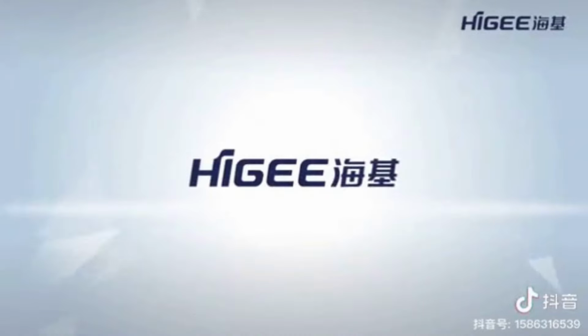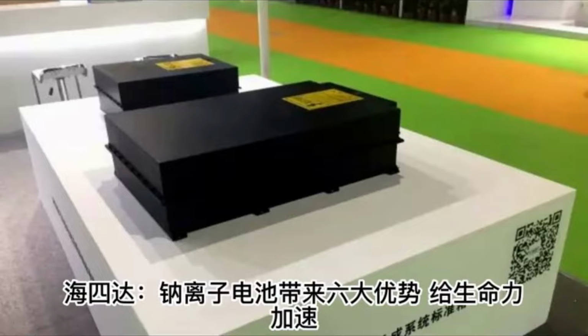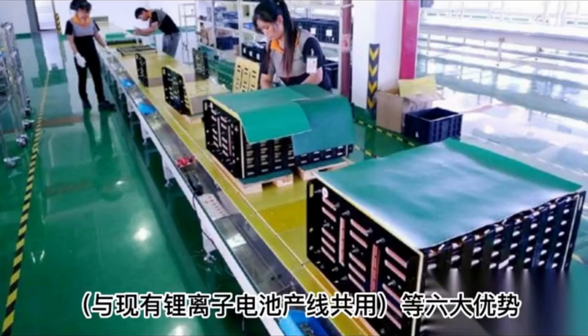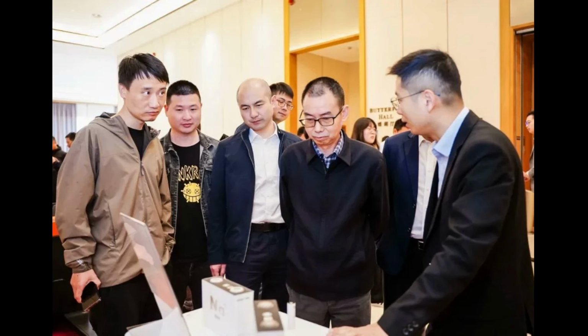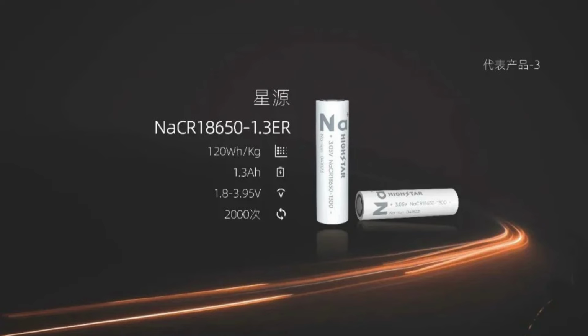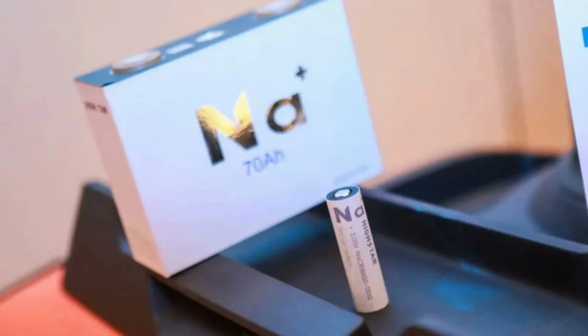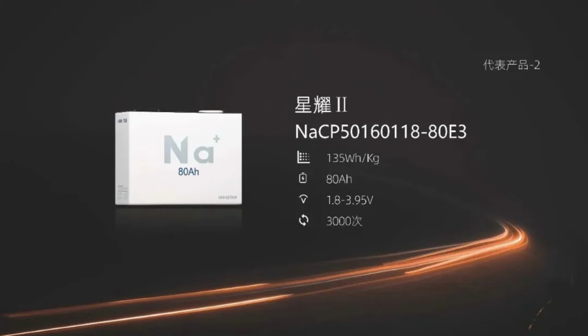The next on our list is Jiangsu HIGHSTAR battery manufacturing in China. The company recently published 3 of its Star series sodium-ion battery cells, which are cylindrical and prismatic cell formats, having a capacity of 1.3, 70, and 80 amp hours. The cells can achieve energy and volumetric densities of up to 135 watt-hours per kilogram and 240 watt-hours per liter, with a cycle life of up to 3,000 cycles.